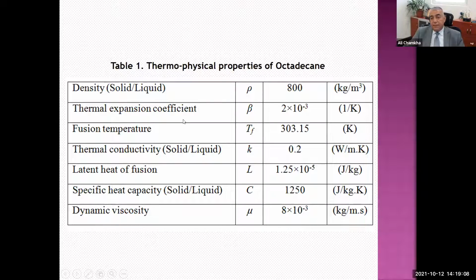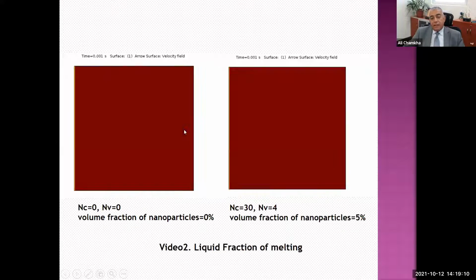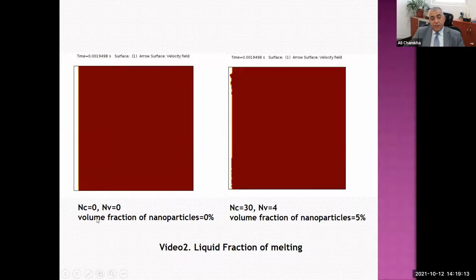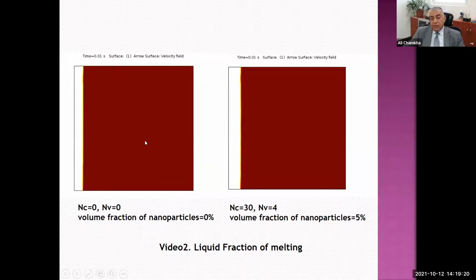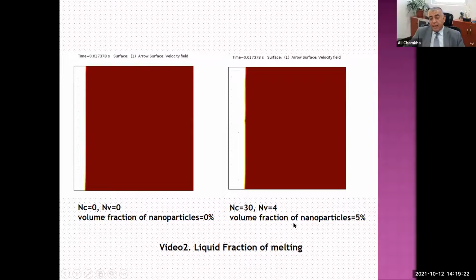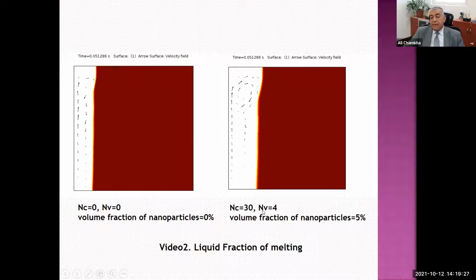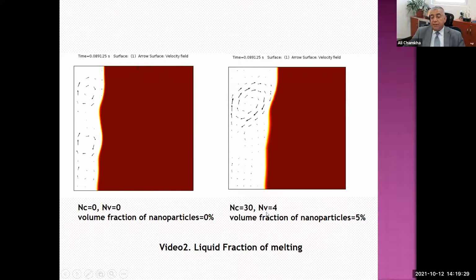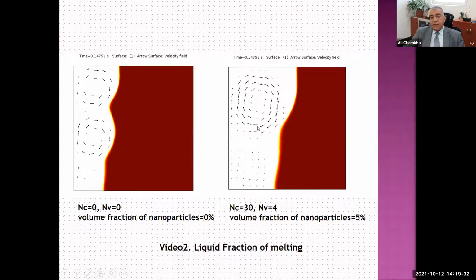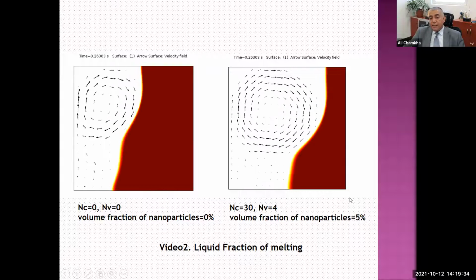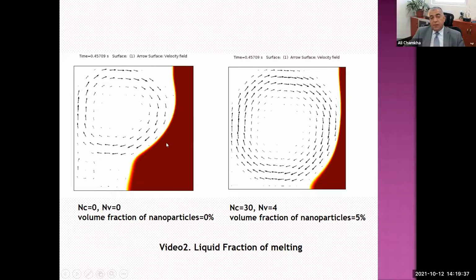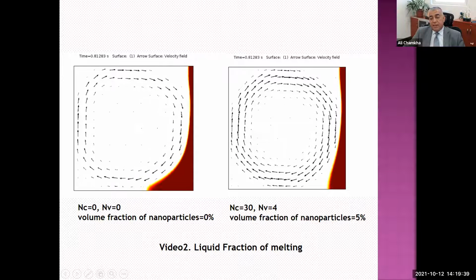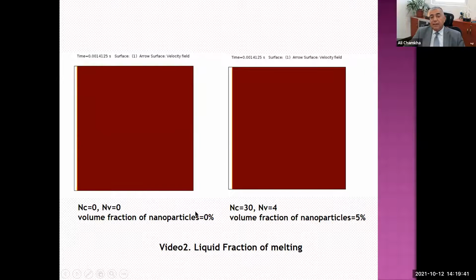These are typical data. If you look at the results, I'll show a small video here. Here we have NC equals 0, MV equals 0. That is base fluid. We don't have any nanoparticles. Here we have volume fraction of nanoparticles 5%, and NC and MV, the coefficients of thermal conductivity and viscosity, set to these values. You can see that when you have nanoparticles, you have faster melting. As you can see, the front is moving in this direction. This is delayed for the base fluid. So you'll see enhancement.